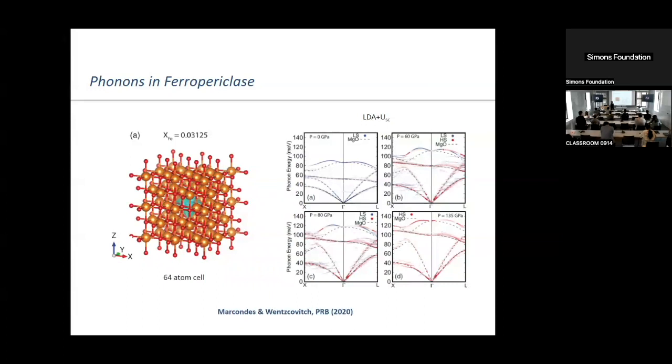And more seriously, 2 questions. One is, how sensitive is this to the value of U? I mean, this is DFT plus U, right? Yeah. So where does the U come from and how much? Yeah, U is calculated by linear response. Okay. That's where it comes from. The interesting thing is, vibrational frequencies don't depend so much on U, or even on the functional, but that's a second order effect on the free energy itself. They affect the transition pressure, for sure. You can move the transition pressure back and forth because that's at the point where the enthalpy difference is zero.